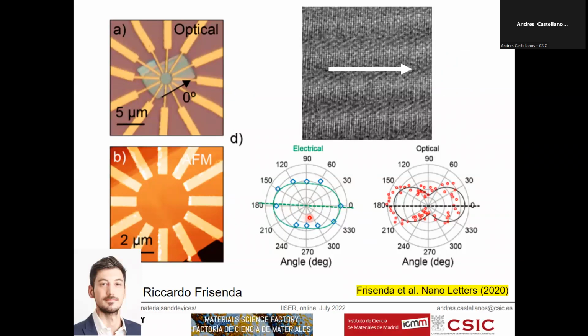And if we do TEM in the same flake, we see that this direction is parallel to these ripples that we saw. What happens is that even though these layers interact with each other through weak van der Waals forces, these interlayer forces are strong enough to slightly deform the lattices according to this moire pattern, in order to minimize the forces between the lattices. Therefore you get a strain pattern following these moire directions. This strain pattern is the one changing the electrical conductivity, and because of the anisotropy in the electrical conductivity, you get an anisotropy in the transmittance.